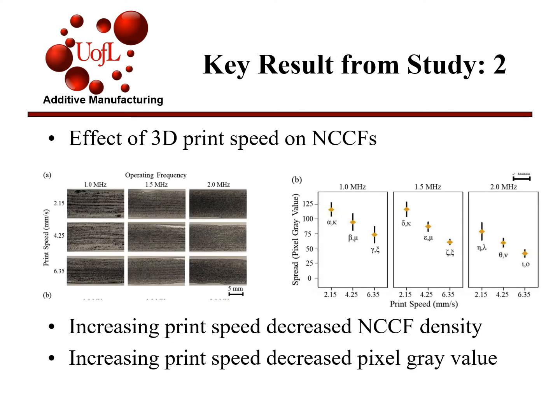Study 2 looked at the effects of the 3D print speed on these nickel-coated carbon fibers. The key result from this study showed that increasing the print speed actually decreased the clarity of the aligned nickel-coated carbon fibers. And this was mainly because it decreased the density of these fibers within the polymer resin, resulting in it making it harder to align and decreased mechanical and electrical properties.